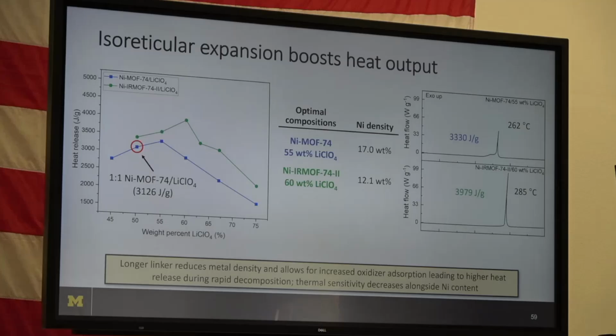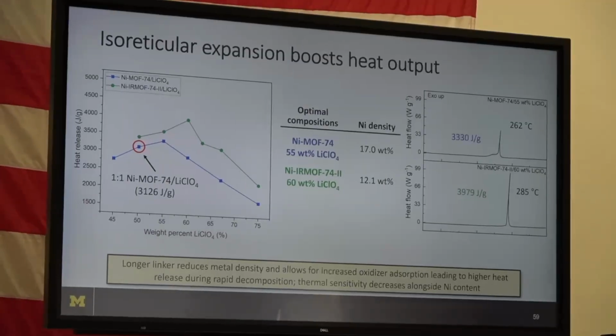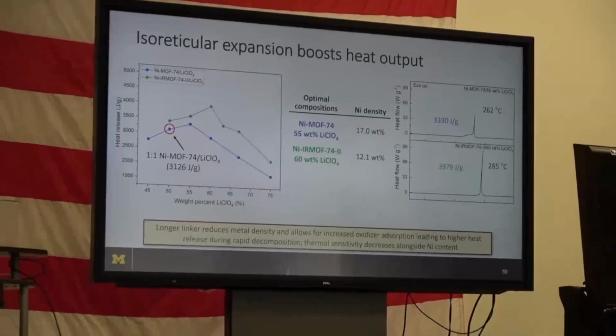And we find that that maximum heat release goes up in the larger pore MOF, and it's shifted to a higher loading of the oxidizer. And by DSC, we can see more heat is being given up. A lot of this is because the metal is kind of dead weight. It's not giving us a lot of heat in this reaction.